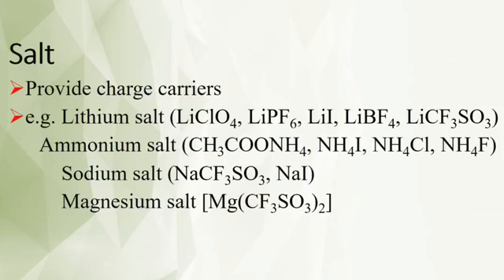And the second requirement is a salt. Salt is the one which will determine the application of the polymer electrolytes. Okay, if you look at the lithium salt, for example, if you use an appropriate lithium salt, that means we are showing that this can be used for a lithium ion-based supercapacitor. If you are using sodium salt, then it is for a sodium ion-based supercapacitor, and same for magnesium.